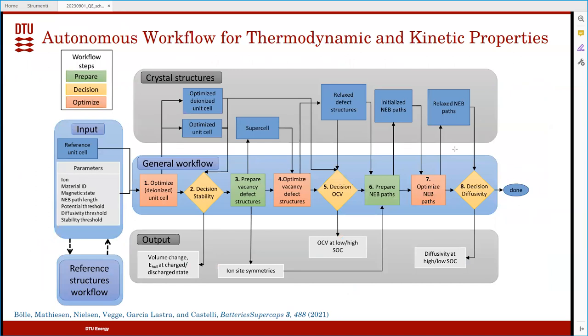So this is what the workflow does in the back. You calculate an optimized unit cell, calculate stability with and without the cation, the intercalating ions. We can calculate vacancies, you can calculate NEBs, so the nudged elastic band method, to calculate the pathways and get the diffusion. And this is all something that happens automatically, right? You can see all the arrows going up and down. What you need to remember is the input.